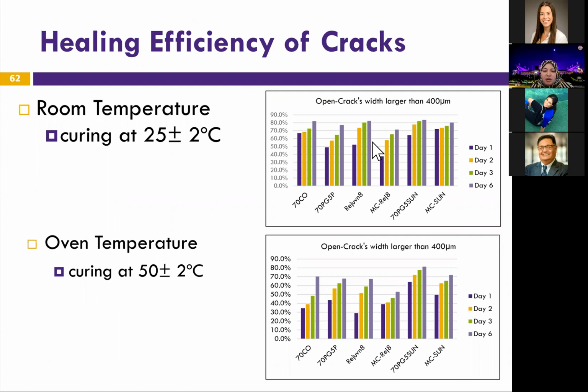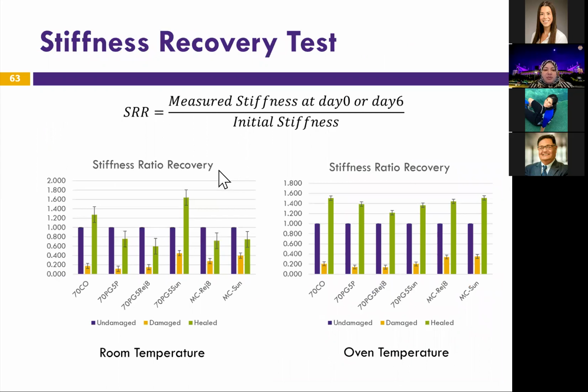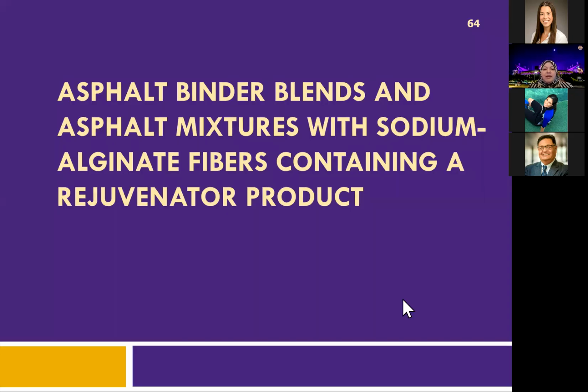And as you can see here, the rejuvenators are healing very well, whether the sunflower oil or the Rejuve8. The microcapsules are lower than the rejuvenator, and that's expected, of course, because not all capsules are going to break. But whatever capsules break are the ones that are in the line of the crack. For stiffness recovery, you can see this is the original stiffness, damaged stiffness, and then healed stiffness. And as you can see, the sunflower oil had the highest stiffness recovery ratio, both at room temperature and oven temperature. Now I'm going to talk about the second delivery method, which is the fibers.